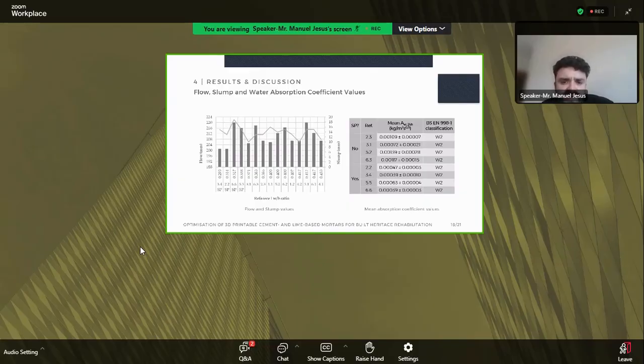So the experimental results show that the flow ranged between 201 millimeters and 220 millimeters, which aligns closely to the literature, as you see on the graphic on the left. So the slump test results presented values between 10 millimeters and 20 millimeters, which also fall within the acceptable limit. So these values indicate satisfactory shape retention, a critical indicator for high buildability.